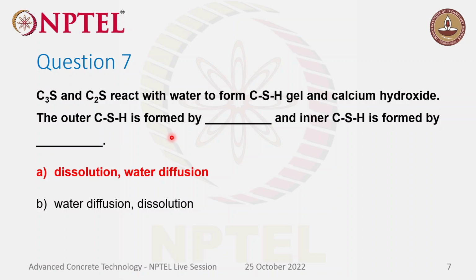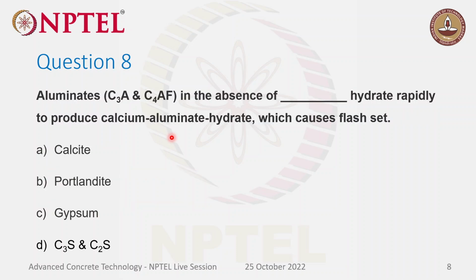Coming to inner CSH, the water should break the barrier formed by the hydrates around the cement grain and diffuse. So inward water diffusion happens, then inner CSH will be formed. We all know that outer CSH is more porous because it forms by dissolution from the reaction products. Inner CSH is more dense because water gets into the unhydrated cement grain and reacts to form inner CSH. Now let's move to question number 8.